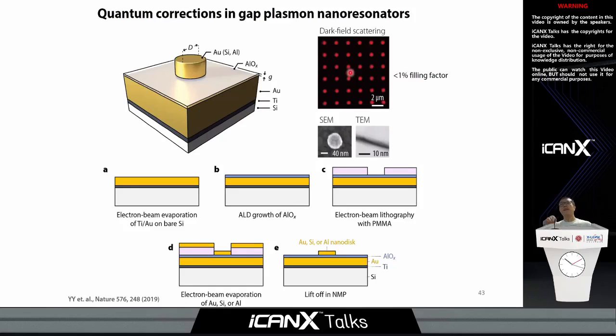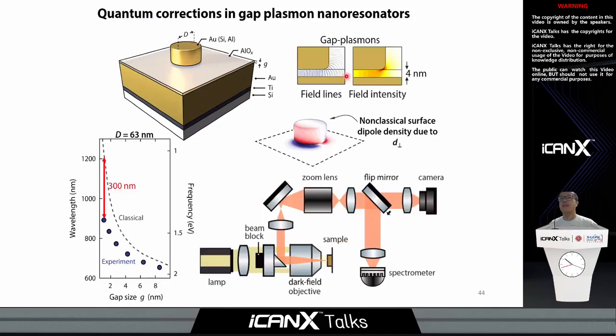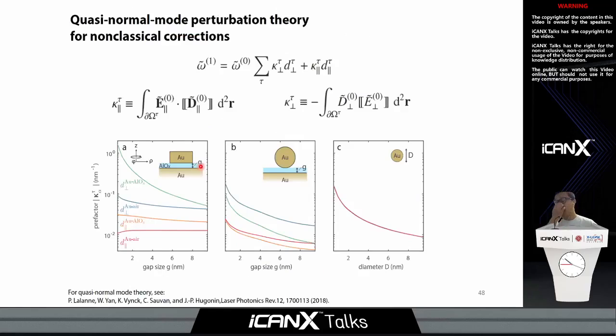I know that if we replace this nanodisk with spheres, this will increase the outcoupling efficiency significantly. This is the reason why, for example, seminal works by the Baumberg group and other groups adopt nanospheres rather than nanodisks, because of the high efficiency. But in those structures, as I show here, the non-classical correction is much smaller. So it's a kind of trade-off, but because our work focused on quantifying these non-classical corrections, we chose to work with low efficiency structures. Hope that this can address the question. Good.